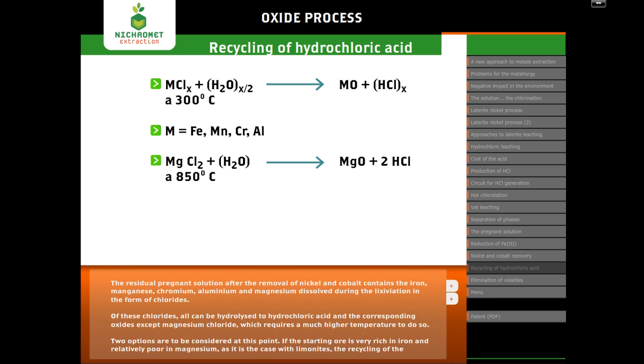If the starting ore is very rich in iron and relatively poor in magnesium, as it is the case with limonites, the recycling of the hydrochloric acid can be done with a mixture of chloride incorporating the magnesium chloride, sulfuric acid being added to make the magnesium soluble as sulfate. Then, by water leaching of the residual mixture of oxides, magnesium sulfate can be recovered.